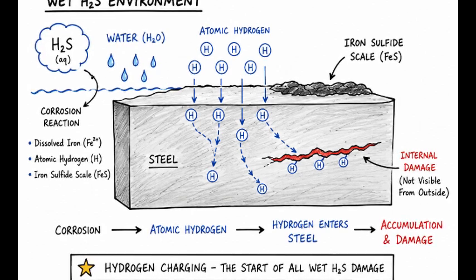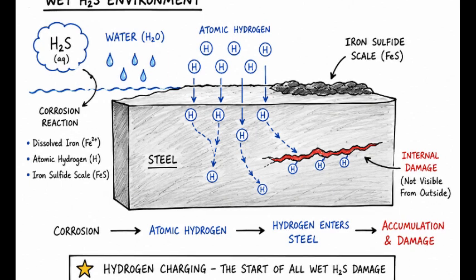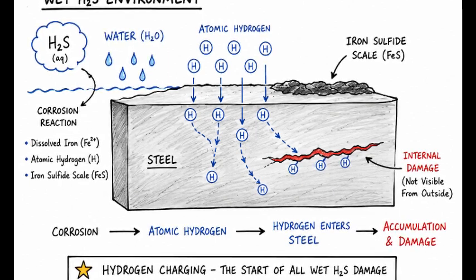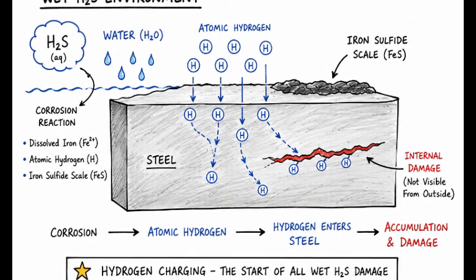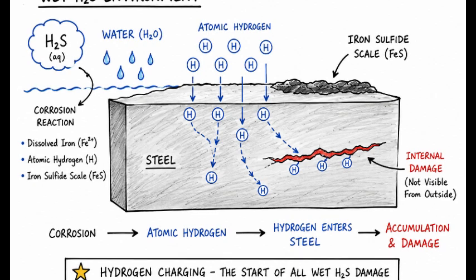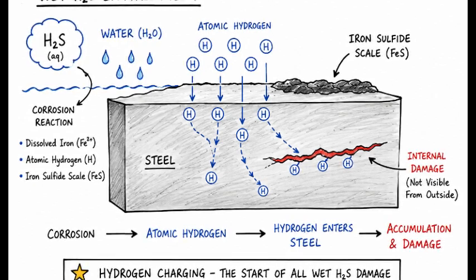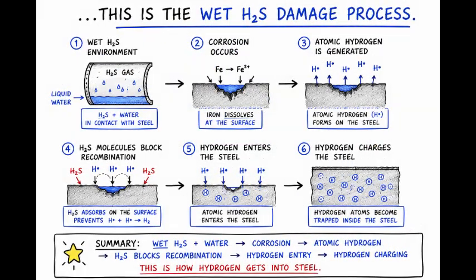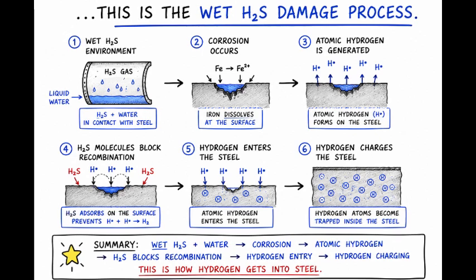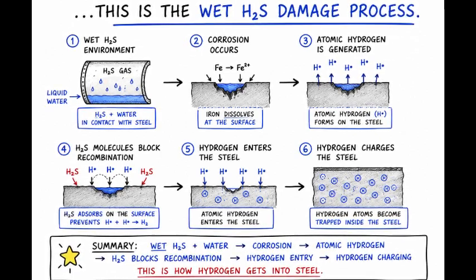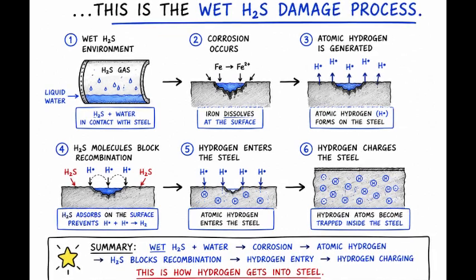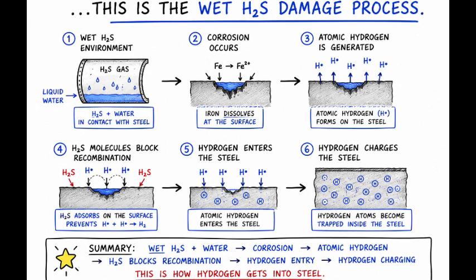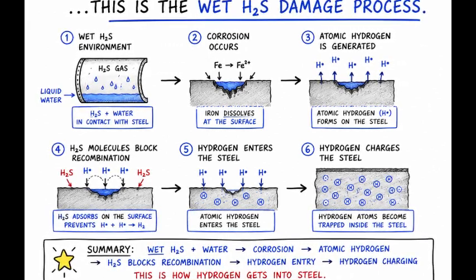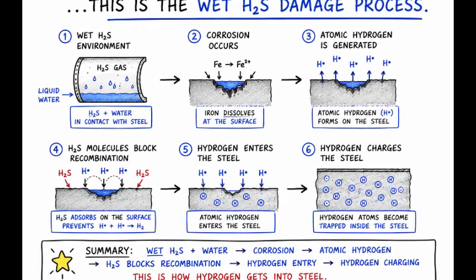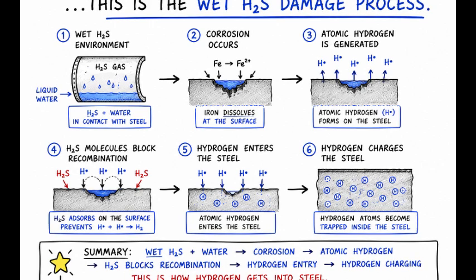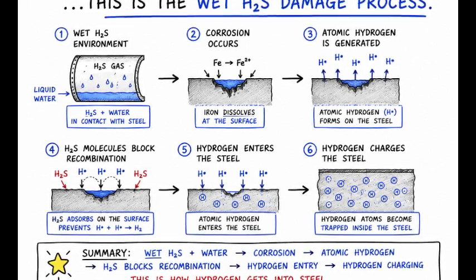The hydrogen story, where everything begins. When carbon steel or low-alloy steel is exposed to water containing H2S, corrosion occurs. The corrosion reaction creates dissolved iron, atomic hydrogen, and iron sulfide scales. Normally, atomic hydrogen will recombine at the steel surface to form hydrogen gas and escapes harmlessly. Now, available sulfur in the system, a product of the degrading H2S, changes everything. Sulfur acts as a hydrogen recombination poison, preventing the normal combination of hydrogen atoms into hydrogen gas. This is one of the most important concepts in wet H2S damage.